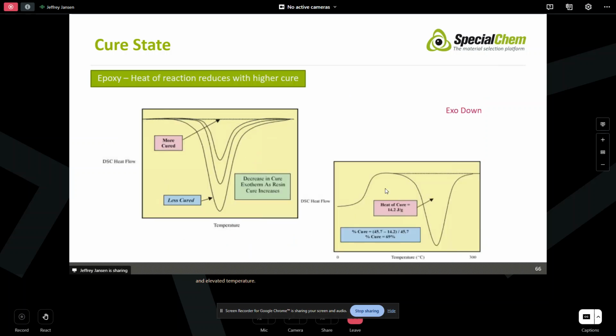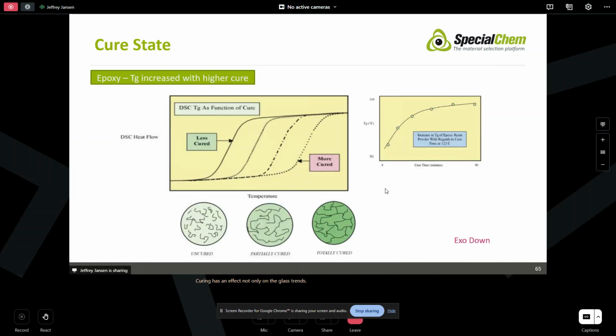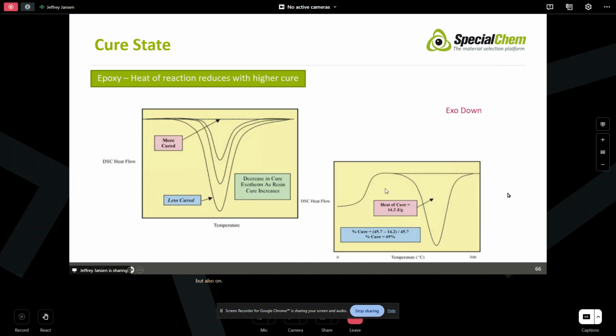Again, the other thing that's going to change is the heat of reaction. So as we heat the sample up, in many cases, thermoset materials will undergo a reaction. Again, exo is down in this particular case. And so we have this transition. If we have a less cured material, we're going to see more residual cure that's going to happen during the test. If we have a more cured sample, there's going to be less of that. So again, curing has an effect not only on the glass transition, but also on the amount of cure that's left. So what we can do is take some raw resin for our thermoset material. We can establish a heat of cure, okay, at say 14 joules per gram.